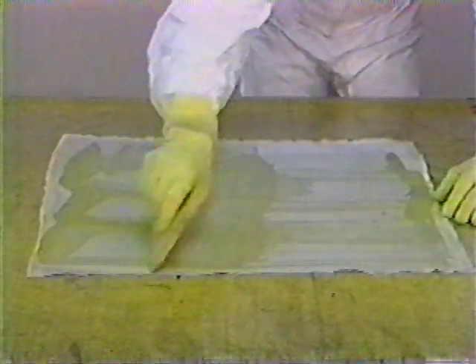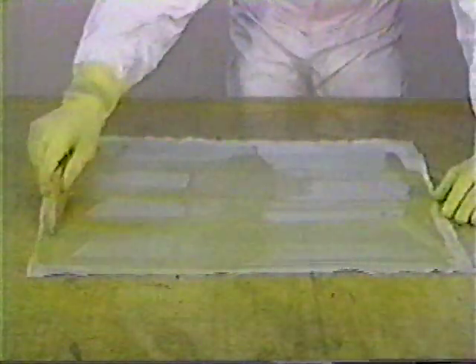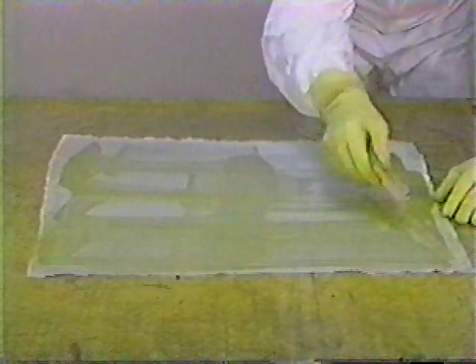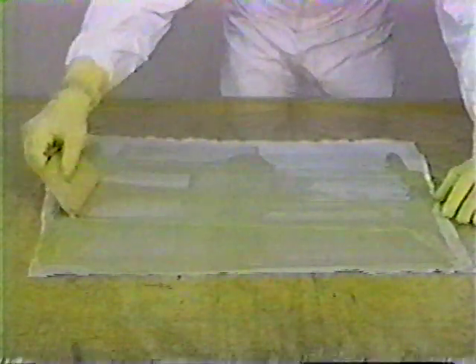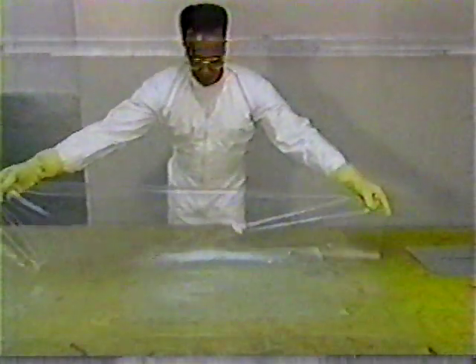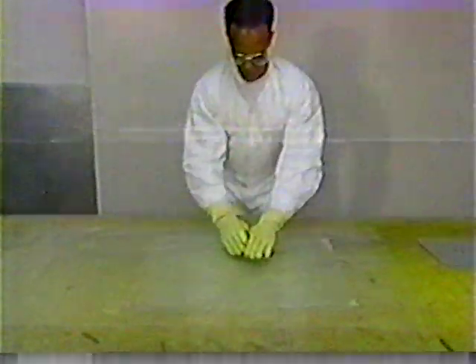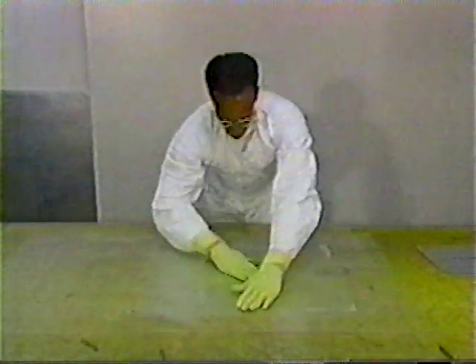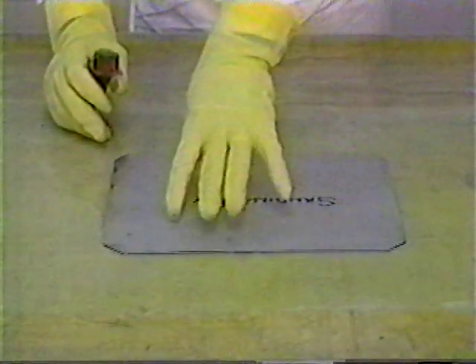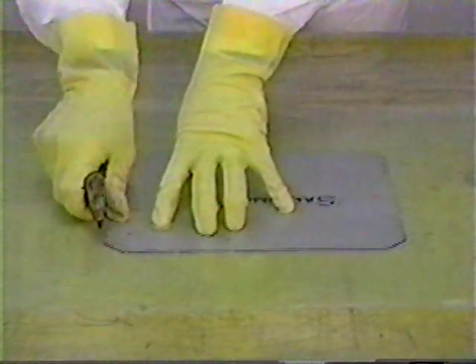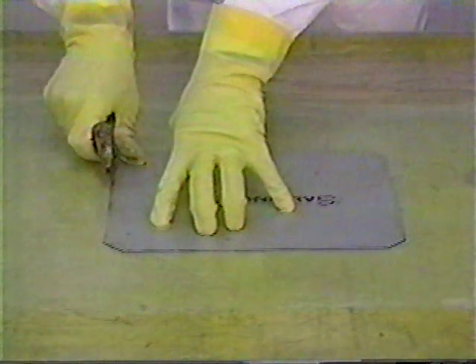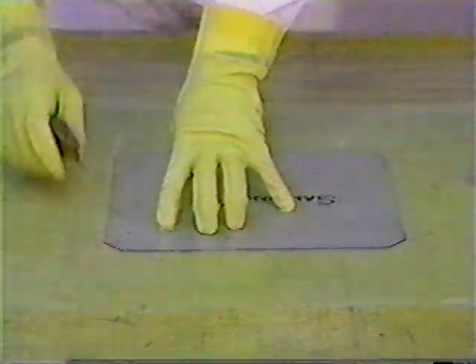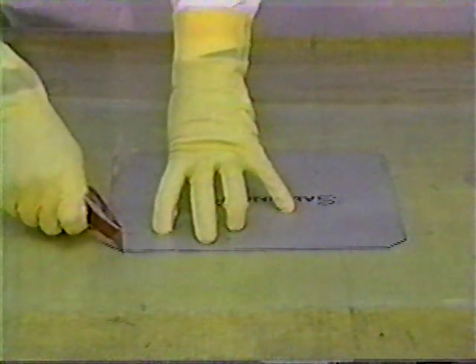Next, thoroughly saturate the fiberglass sanding ply fabric with resin, carefully working it into the weave of the material. Then, place a sheet of non-porous parting film over the top. Use the sanding ply template to cut the fiberglass material. The sanding ply will also extend 3/4 of an inch beyond the edge of the last repair ply.